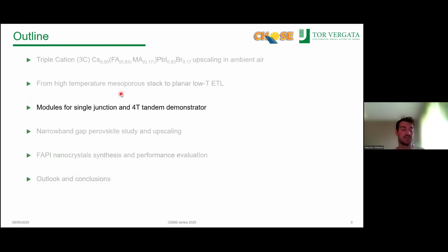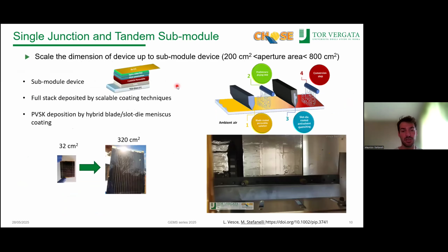So once we got all the stack made in ambient air and at low temperature for the whole fabrication, we moved to bigger areas, in this case to sub-module devices. We move to a 32 square centimeter substrate, that is the area of the mini module, to 10 times this one, for an active area of 180 square centimeters and an aperture area that is more than 200 square centimeters, which is the range in which the substrate can be called a sub-module. I will show you briefly the deposition of the perovskite that I already explained.